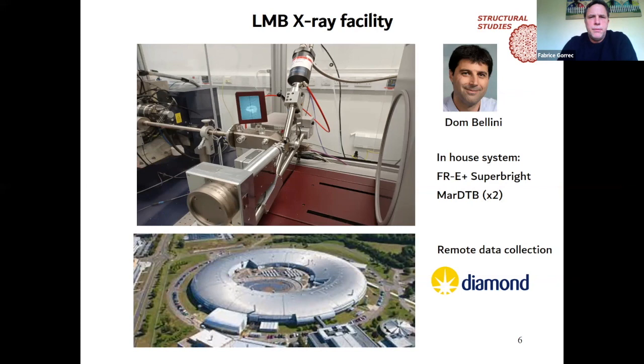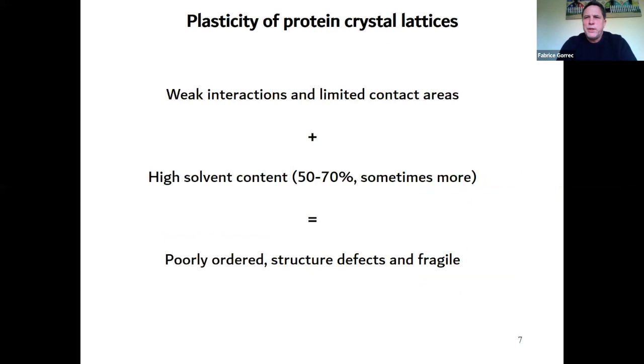Unfortunately, a lot of crystals don't diffract as well as expected, even when they look nice, like the one I showed earlier. The underlying reason for that is basically that the crystals are made with weak interactions, and there are limited crystal contact areas. Sometimes crystals are held only with long range electrostatic interactions and a couple of hydrogen bonds. So the density is not there, and there's high solvent content. The result is that most crystals are poorly ordered, and they also have structural defects. They're also very fragile, which makes any manipulation difficult.